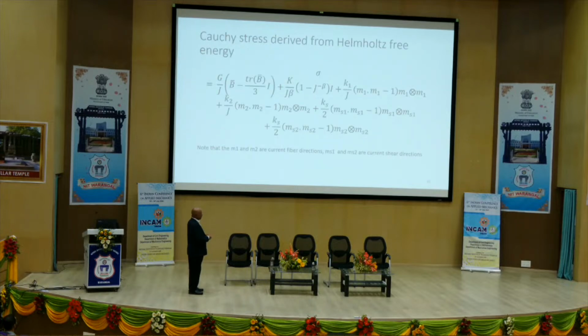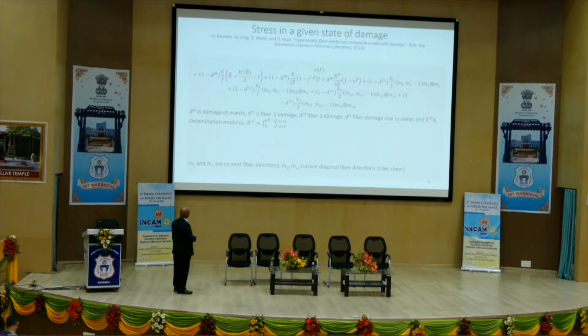Now we differentiate that equation, and you get the constitutive equation. This is the one. That's just the derivation from the differentiation of the previous term. Now you use CDM. That means the first term, the shear modulus, I'm going to degrade using 1 minus d to the power of m. The bulk modulus, again, is degraded by 1 minus dm. That means matrix expansion or matrix contraction. The third term has a damage variable for the fiber, DF1 is for the fiber. Then damage for fiber system 2, and damage due to shear. So you have DM, DF1, DF2, DFS, and then you define them.